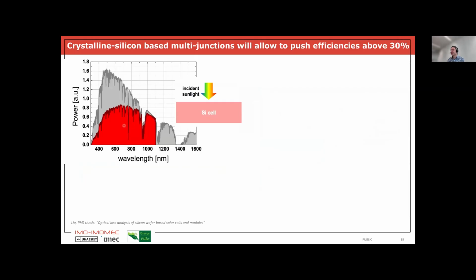So if we look at the single junction silicon solar cell, with which we can now reach 27.8% as a record efficiency value, we see that we lose a lot of the energy of the incoming light, especially because of thermalization losses. So all this gray part here is energy that is lost from photons that do get absorbed by the silicon solar cell, but where, because of thermalization losses, we actually lose this energy. So we only use part of the energy of the incoming photon.